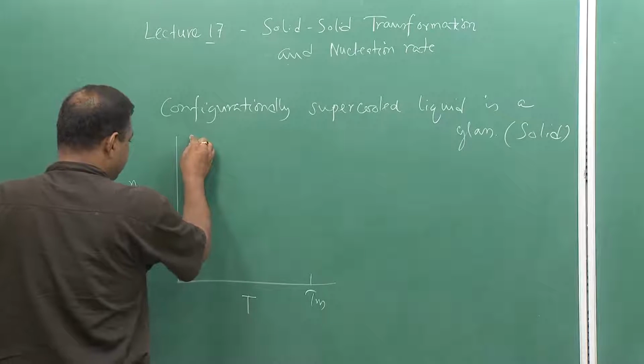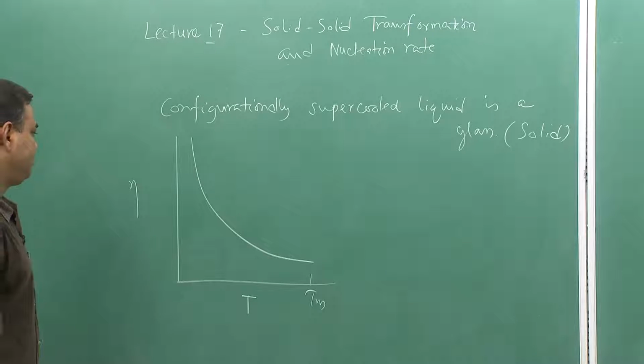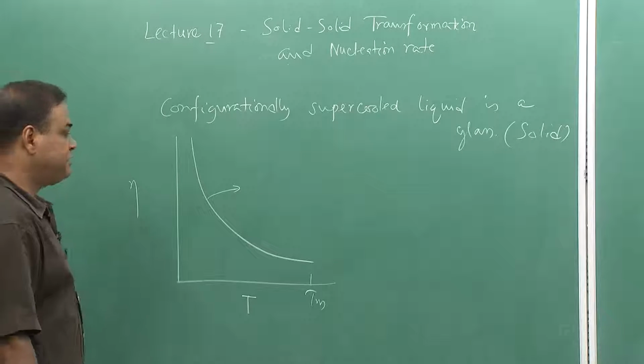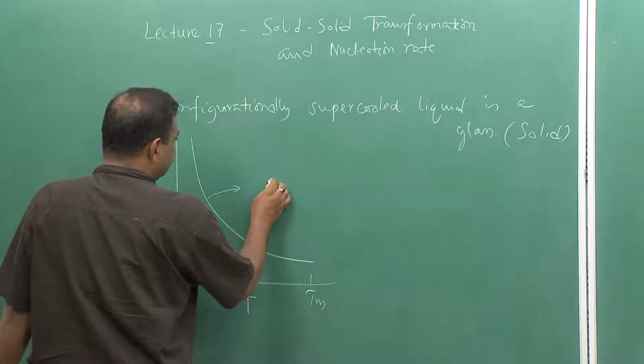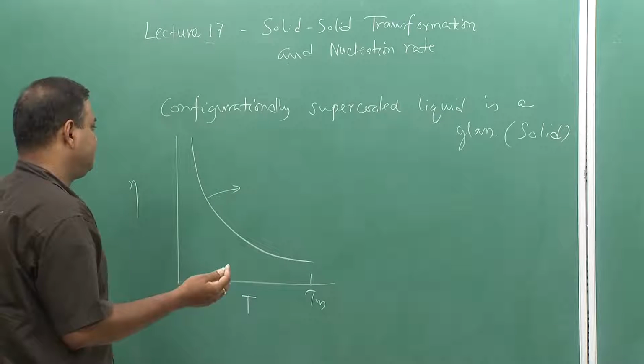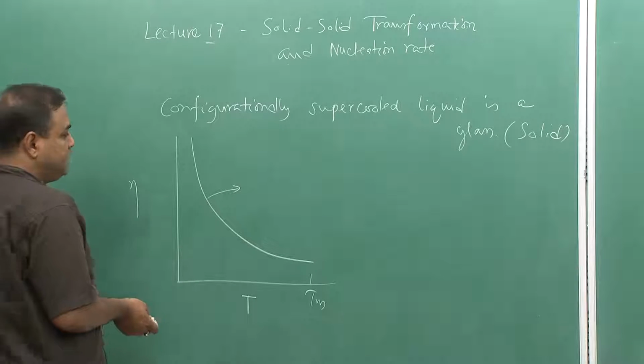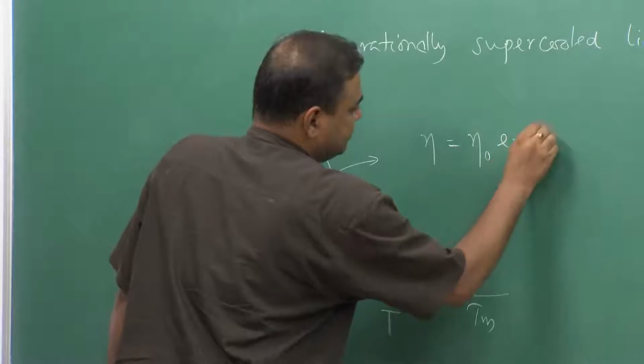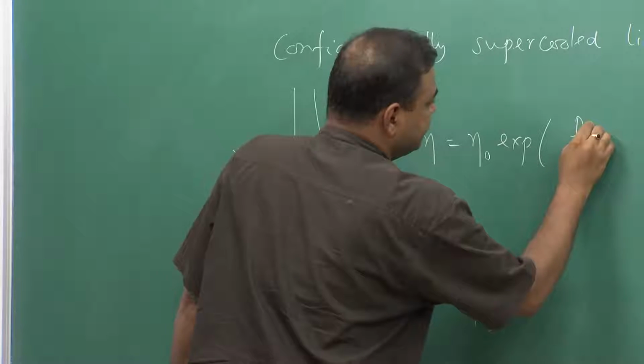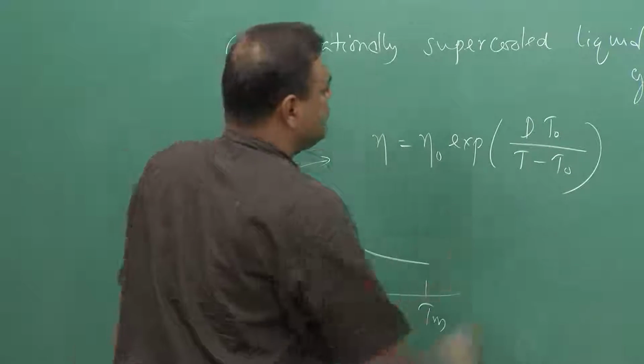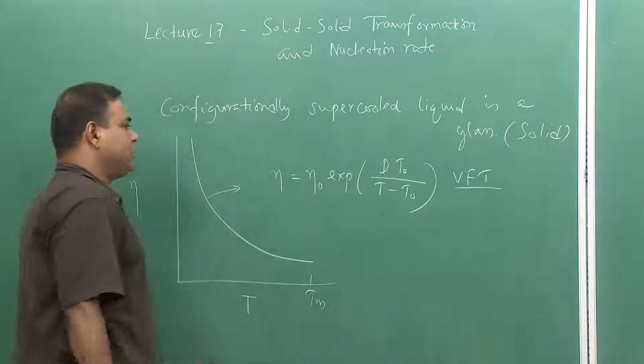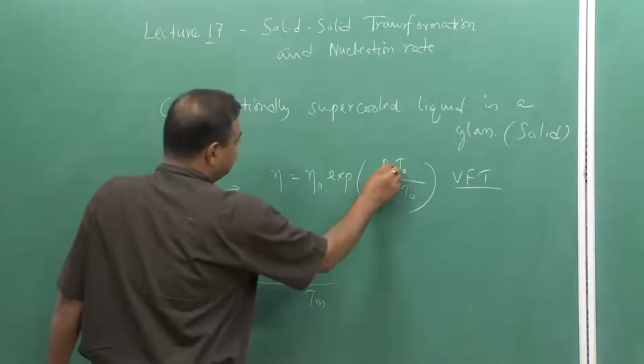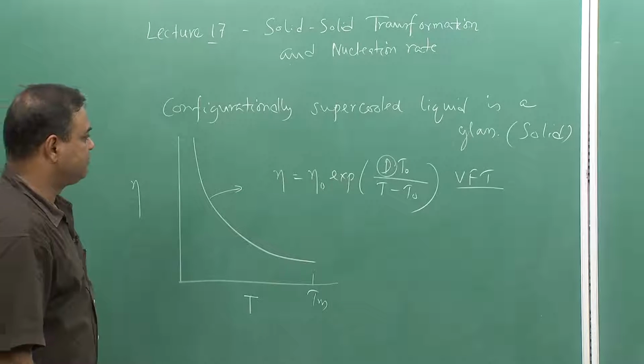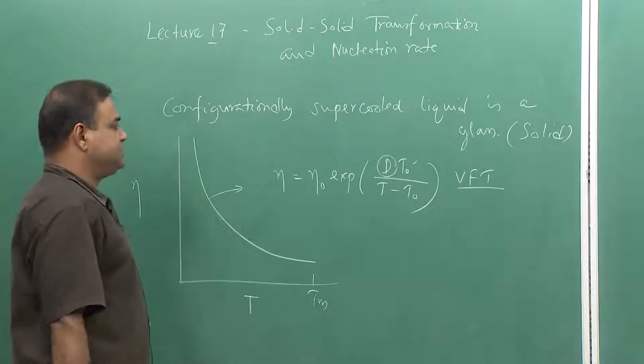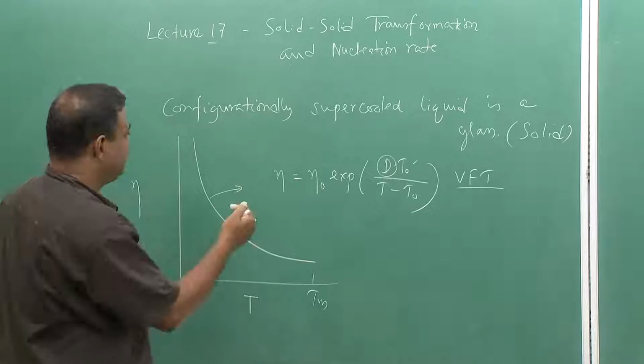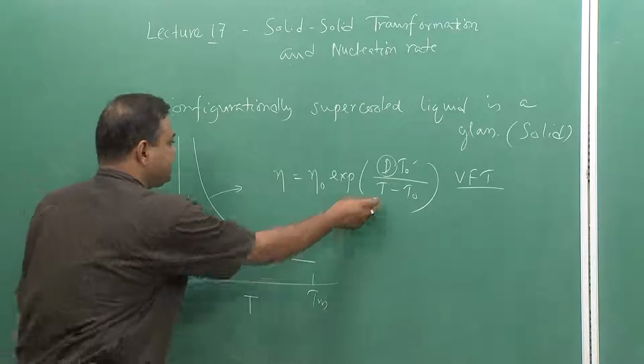Generally, the viscosity variation of the liquid form has a nature like this, which is actually related to Arrhenius increase, and a more refined situation for viscosity change with undercooling we relate to η0 exponential of D T0 over T minus T0. So, this is called the VFT equation, which is the Vogel-Fulcher-Tammann equation, and there D is called the fragility of glass. Now this T0 is a temperature which has a relation to the glass transition temperature, and this is the temperature below Tm.